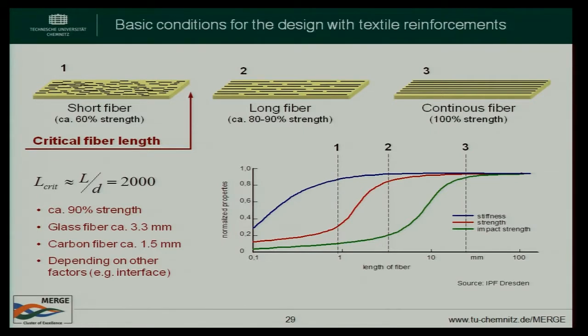Okay, so as you can see here, it depends on whether you use, for example, glass fibers or carbon fibers. It's quite interesting. The critical fiber length is 3.3 millimeters for this application for glass fibers, and 1.5 millimeters for carbon fiber. So this is something you can reach with compression molding, bulk molding, injection molding, more or less. You don't need some really textile reinforcement with endless fibers.